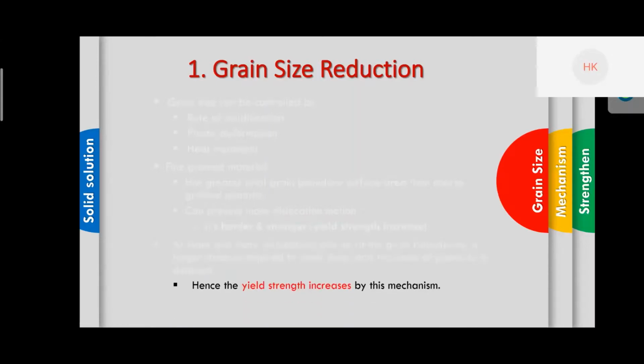So in this case, if we look at the stress strain curve for the stronger or harder material, the curve can be produced higher at a certain yield strength. Okay, so it will increase the yield strength. So the relation between the grain size and the yield strength can be achieved by using this equation. We call it the Hall-Petch equation, whereby sigma y and sigma 0 are related, whereby sigma y is the yield strength. The yield strength is equivalent to sigma 0 plus k_y d to the power of negative half, and whereby d is the average grain size diameter.